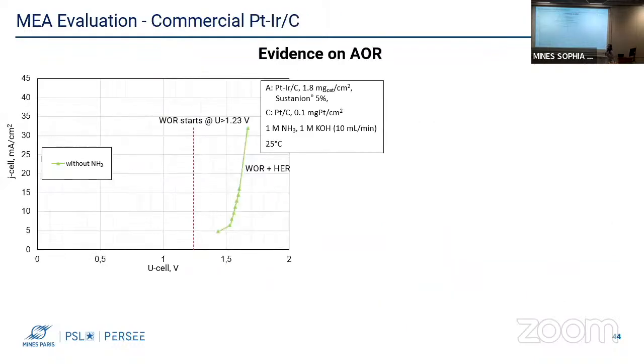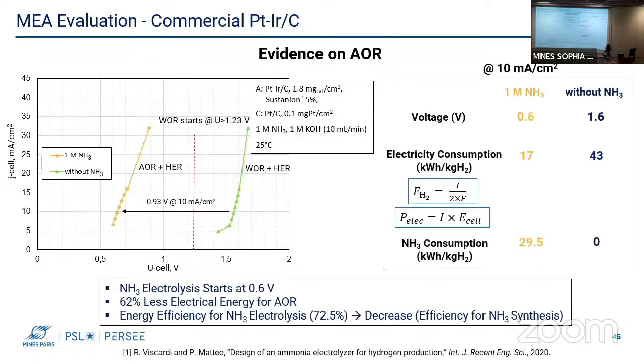First, we start by giving evidence of the ammonia oxidation reaction, and for this we performed two different runs, in the presence and in the absence of ammonia. In the absence of ammonia, a voltage of 1.6 volts is required in order to obtain a current density of 10 milliamperes per centimeter squared. When ammonia is introduced into the system, this voltage decreases to 0.6 volts. It was also possible to calculate the electrical energy consumption as well as the energy efficiency of the system by taking into account the lower heating value of ammonia.